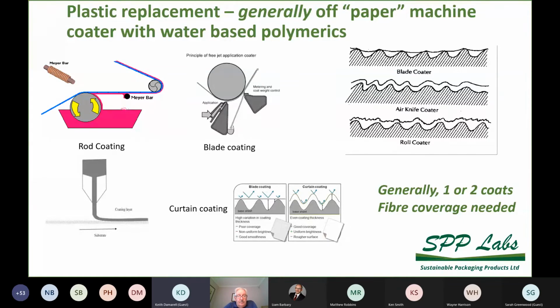If you click it one more time, please, Liam. The coating methods used today normally include some form of either rod application, blade, or curtain coating. Coating solids can be up to 50%, and coat weights normally applied for each of these coating heads are between 5 and 10 grams per square meter. The key goal here is really fiber coverage of that paper with the barrier coating. Because often with rod and blade coating, we're applying coating and then metering off the excess, it tends to give you a slightly uneven coating.